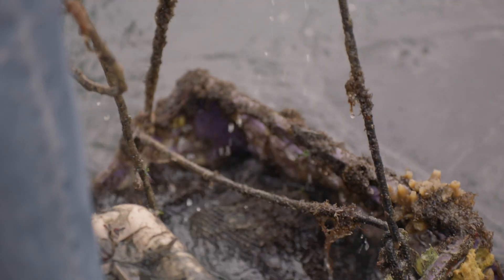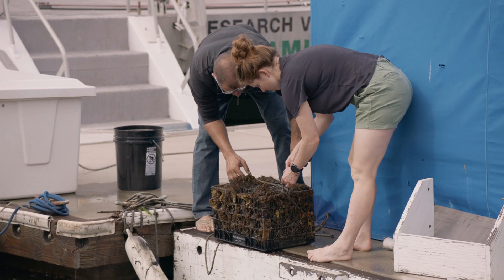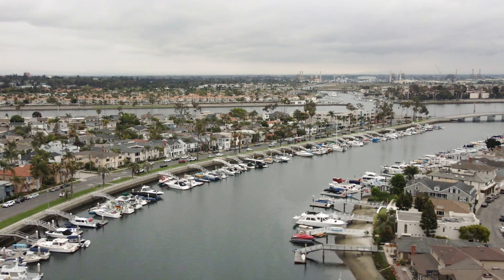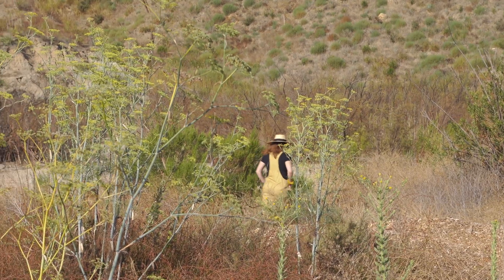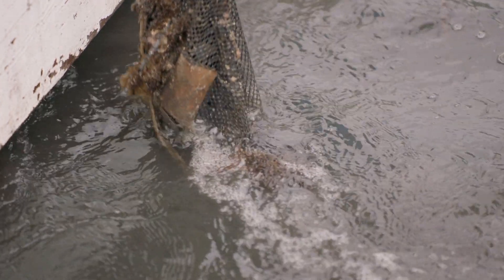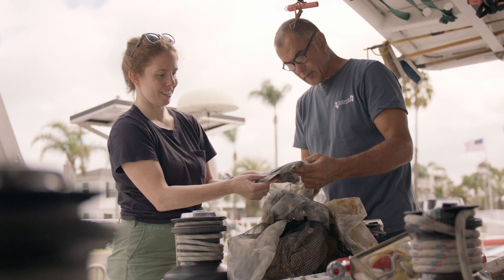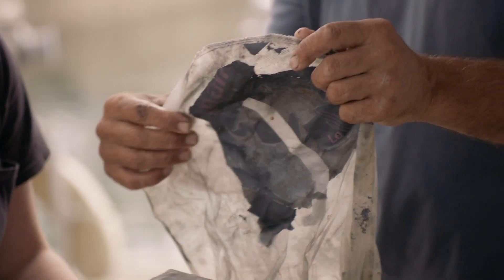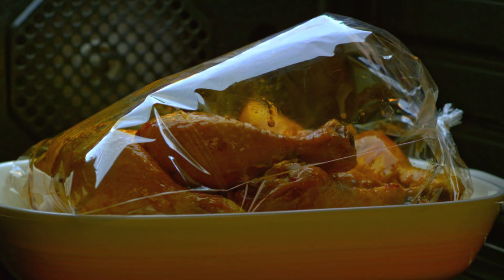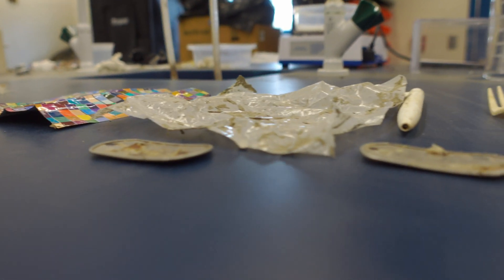What are our thoughts on labeling things as marine degradable, biodegradable, or compostable? The standard of measure for marine biodegradation is typically in a very specific laboratory environment recreating an ocean setting — but that doesn't represent every place that trash could go. In our study, we looked at six different environments and found that measures of fragmentation vary really from place to place. A measure of marine degradability should be in a more realistic setting. Based on this study, we realized there are new materials that can make packaging have less impact if lost to the environment. Some kinds of packaging are perhaps better suited to single-use material — we think thin films are more appropriate for that use, as they fragment very quickly in different settings.